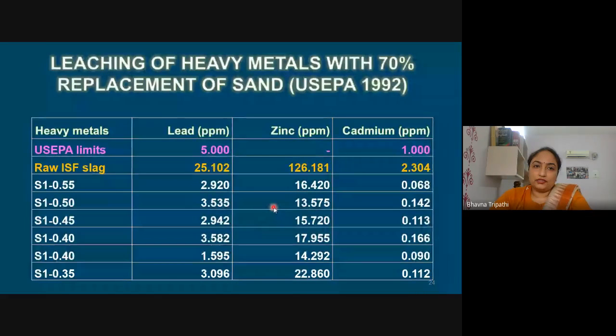by evaluating and measuring the leaching potential of heavy metals. Here in pink, it is written the limits which are allowable. For lead, not more than 5 ppm is allowed, and for cadmium, not more than 1. Zinc has a higher limit because zinc is also given as a supplement, so there was no problem with zinc. However, these two heavy metals were checked. For raw isoslag, the leaching was quite large and it was not acceptable. The leaching of lead was 25 ppm, and that of cadmium was also higher than the allowed limit.